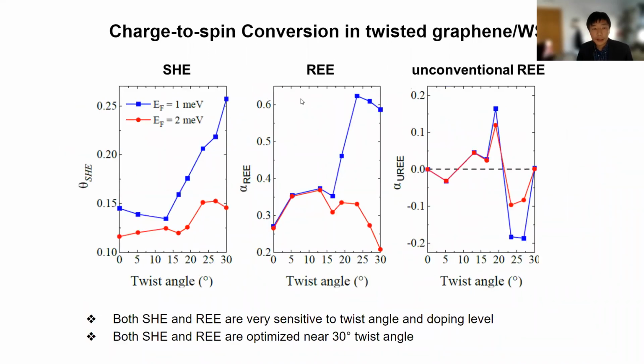Okay, and here is the plot of the spin Hall angle and the Rashba Edelstein angle as a function of different twist angle. We see definitely a very strong dependence of these two phenomena as a function of angle, and the maximum effect occurs at around 30 degrees.